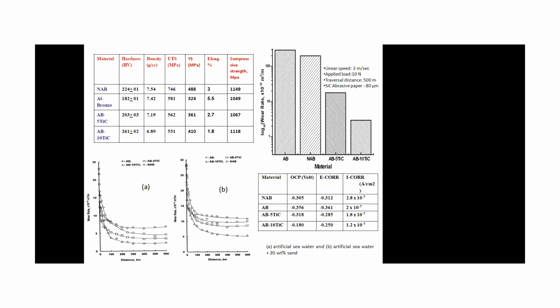Strength wise is more, because for any structural component we have to see not the tensile strength but the yield strength of the material, because failure is governed by the yield strength. Any load applied on the structure generates some stresses, and if the stresses are beyond the yield, then only deformation will occur. So any factor of safety depends on the yield strength. For that, yield strength is more or less safe, and ductility is also okay. We only have to see the wear property. Wear property is okay, and you have also reduced the density, because conventional NAB has a density of 7.54, but the TiC composite has a lesser density.